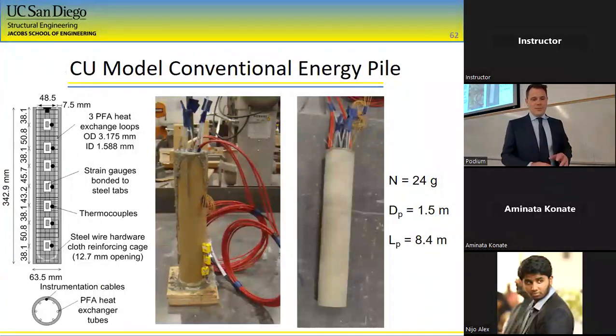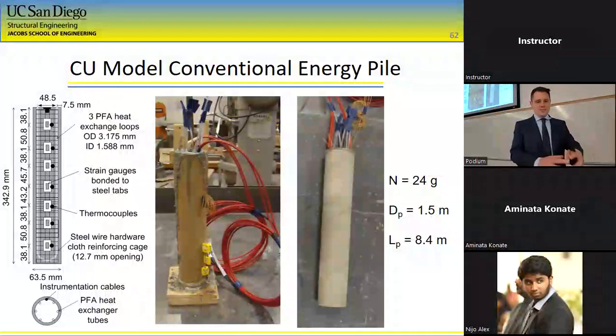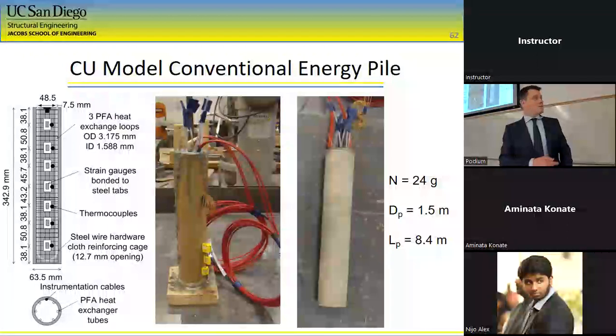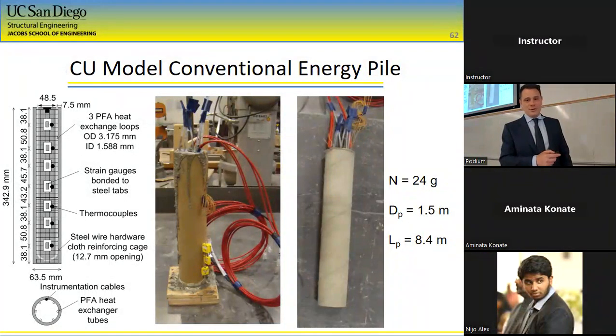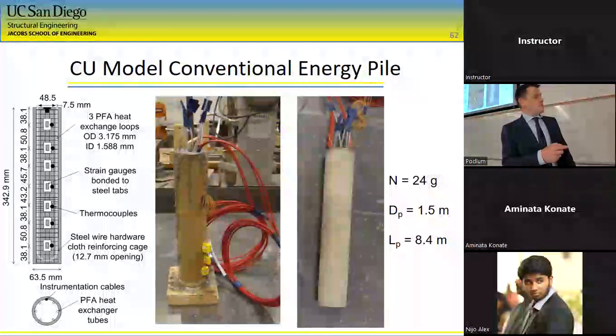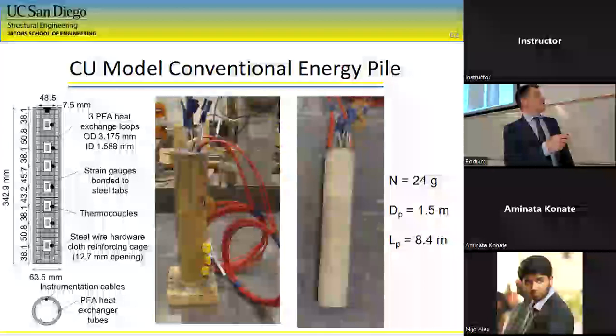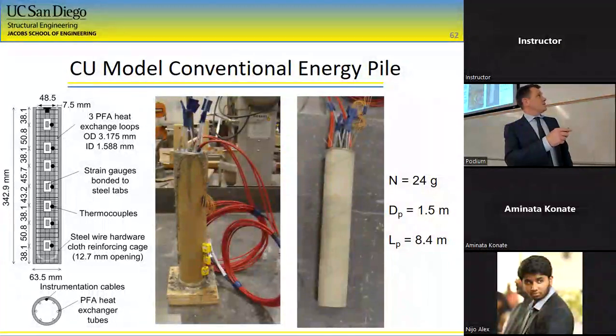So when you do things in the centrifuge, you always get to do some craft projects. You have to make some small scale models of your field structures. So this is our scale model energy pile. This is a floating structure. You can see the cardboard tube and then the lines that are left from the cardboard tube. But we were able to pack a lot of stuff into there. Strain gauges at different depths, thermocouples, reinforcement cage, and then our heat exchange pipes.